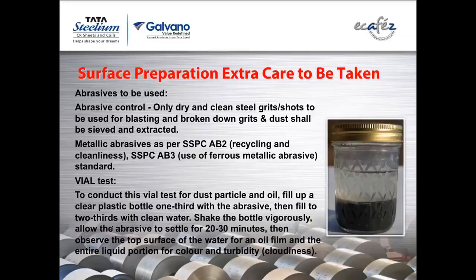So now this particular test is you have to take some amount of grit into a bottle. Even the normal water bottle is good enough. Fill it up to this much by the grit, taking it from your production, have water to this level, almost 2/3 of the bottle. Shake it vigorously and keep it for 20 to 30 minutes. The grit will settle down. If grit has dust or any other things, there will be a turbidity in the water, and on top of that water you will be able to see oil floating.